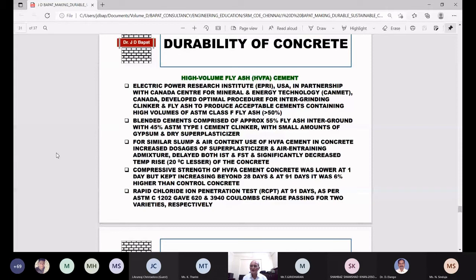For similar slump and air content, use of HVFA, that is high volume fly ash cement, in concrete increases the dosage of superplasticizer and air entraining admixture, delays both initial setting time, IST, and final setting time, FST, and significantly decreased the temperature rise of the concrete. This is very significant: the last line is very significant, that you have reduced the temperature rise in concrete by more than 20 degrees centigrade.